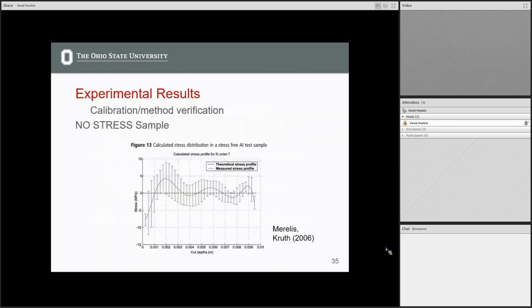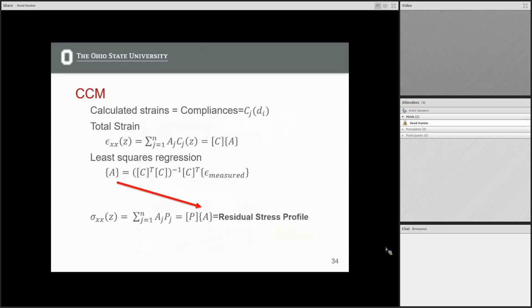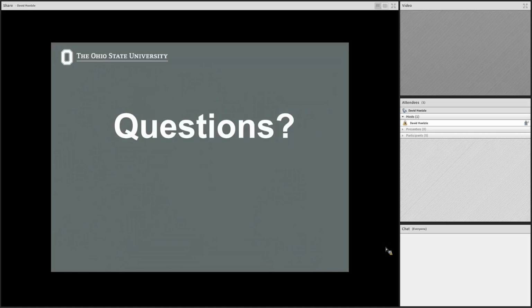Let me see if I have that graph. I do not. So they go into a little bit about how they're justifying the fact that they can use this methodology and compare it directly to their crack compliance method in the paper itself. One of the interesting things that they did was that they took a look at a part that had no stress, so it was an annealed solid block. Using this methodology, they proved that it had very, very low stresses at the surface, so close to zero within